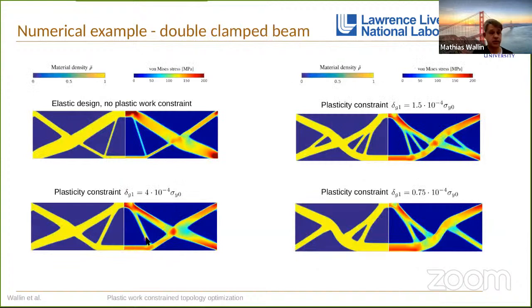I think this is the final example. It's a double clamped beam. If you have the elastic design, this is also well known. We have seen that in many papers. But now if we allow a certain amount of plasticity, so the peak plasticity value, if we allow that to increase, we can see that the design more and more adapts to the loading. If we allow quite a bit of plasticity, we see that we get a completely different design, way far away from the elastic design.